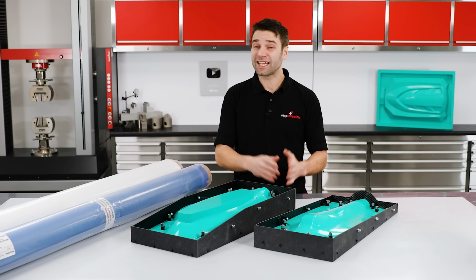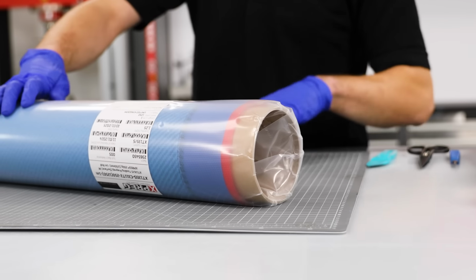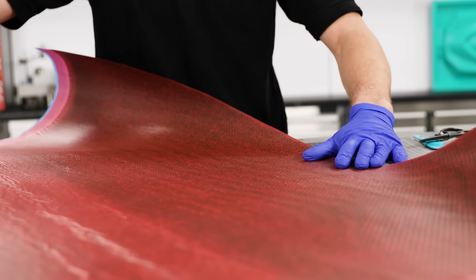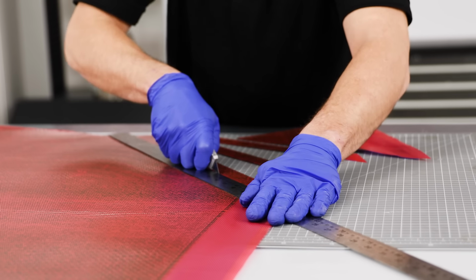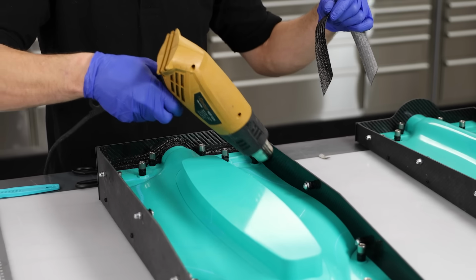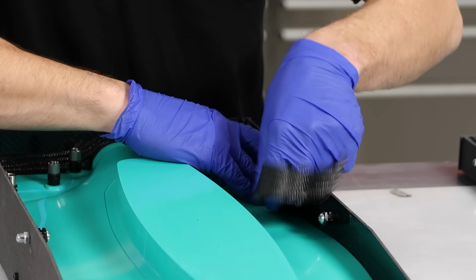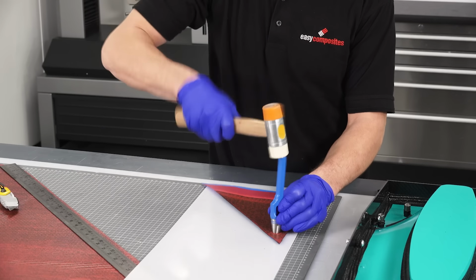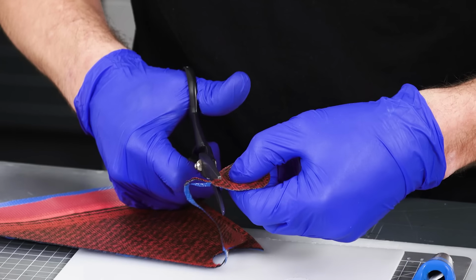The first step in the process is to cut some narrow 30mm wide strips at 45 degrees out of the surface ply, and then place these into all of the sharp corners. Then a patch can be laid over each of the clamping bushes. A wad punch is a great tool for creating the hole in the patch.